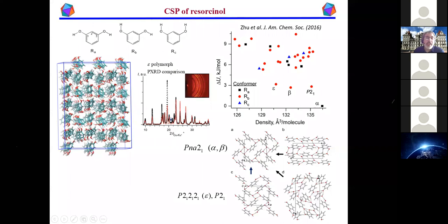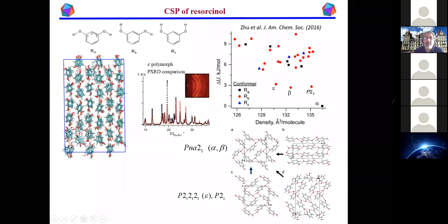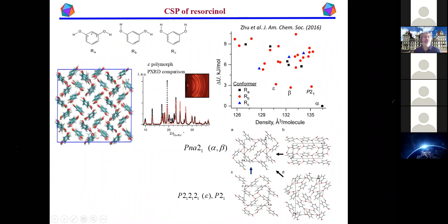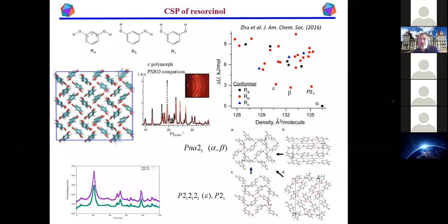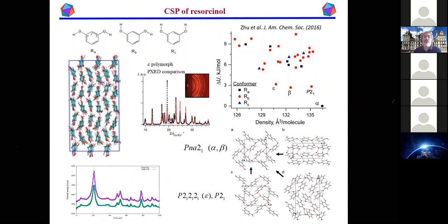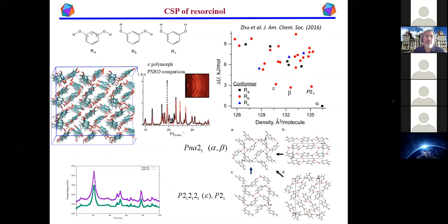And you visit a couple of different structures along the way if you compare what you see in the trajectory to what you see down here. And there's a rather large energy barrier that you have to cross in order to get over to the alpha polymorph. So while it is true that the energy difference is only a few kilojoules per mole, there can be large barriers that separate these different polymorphs from each other, which is why it's difficult to see the actual structural transition.